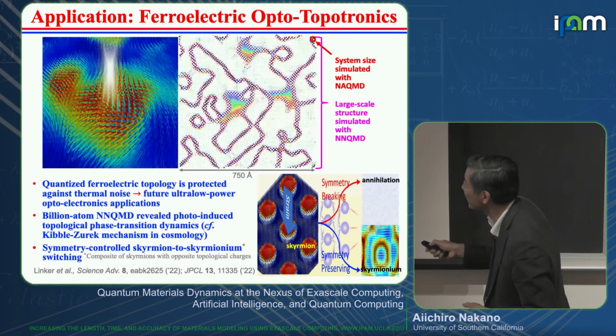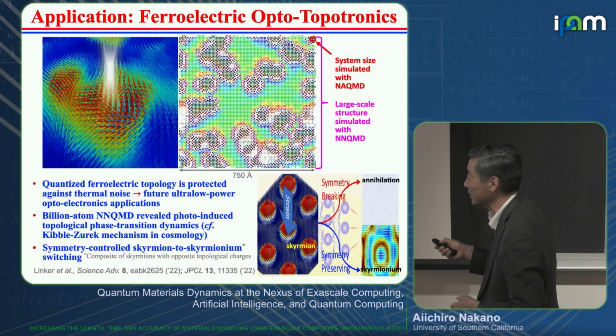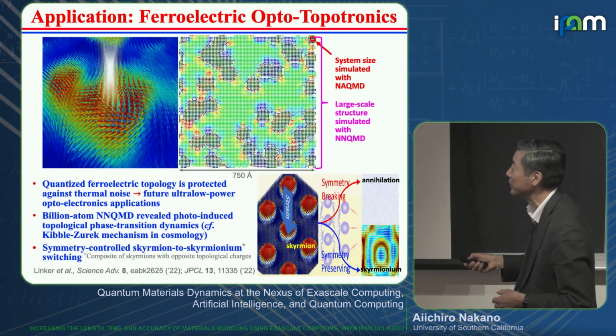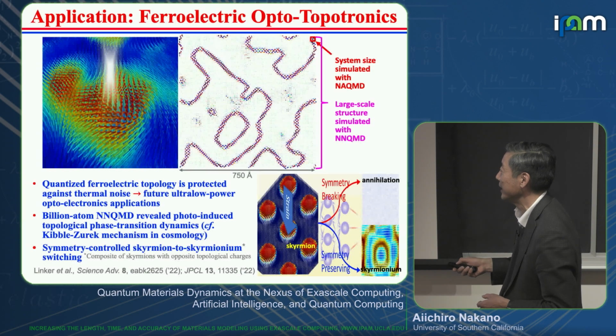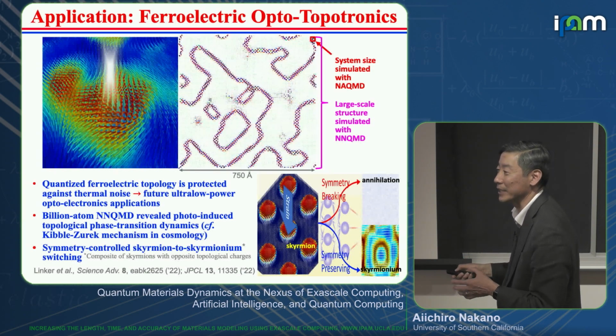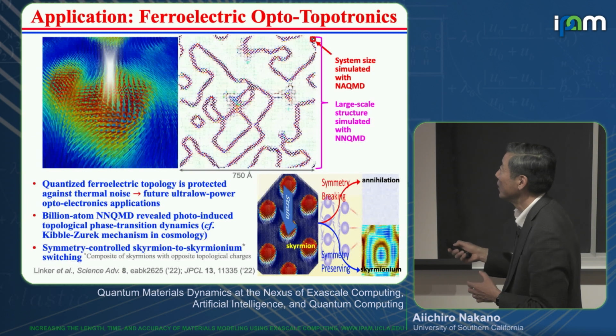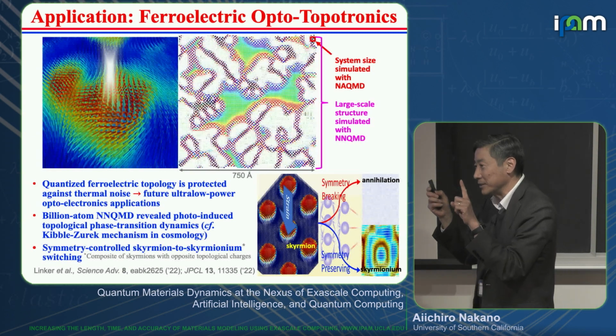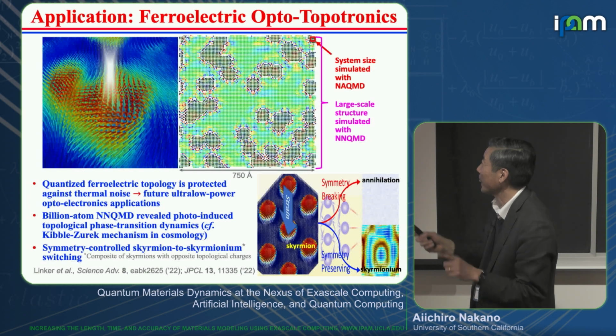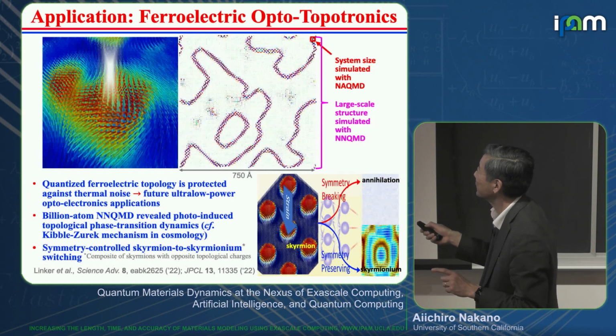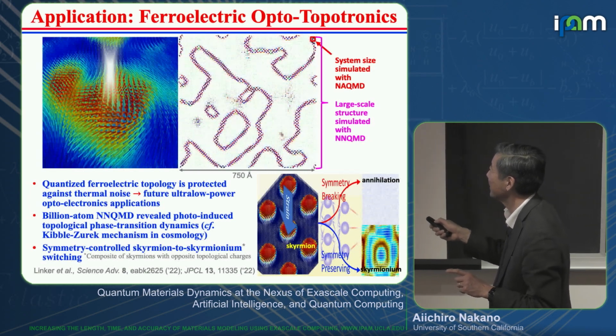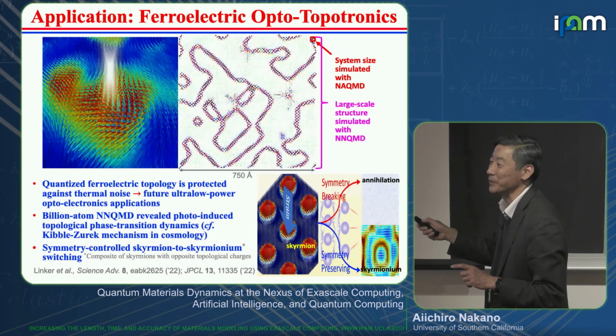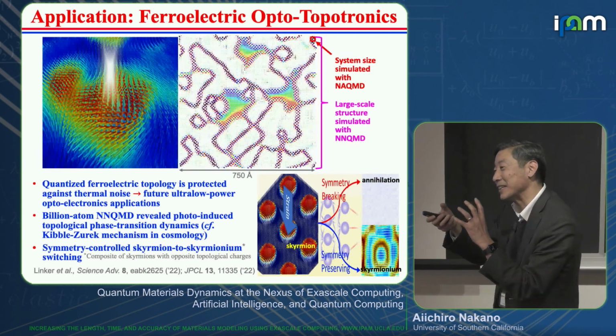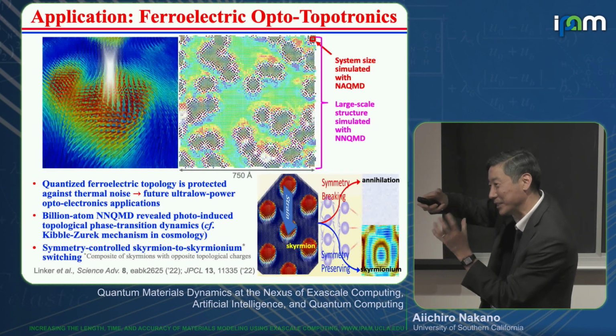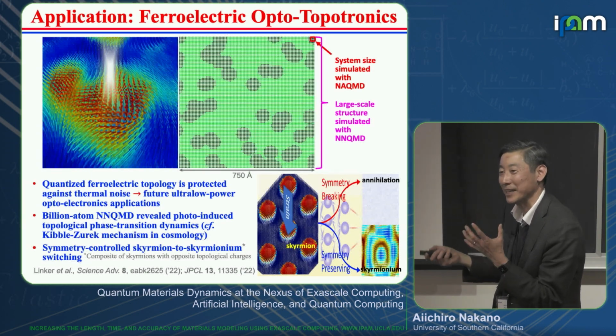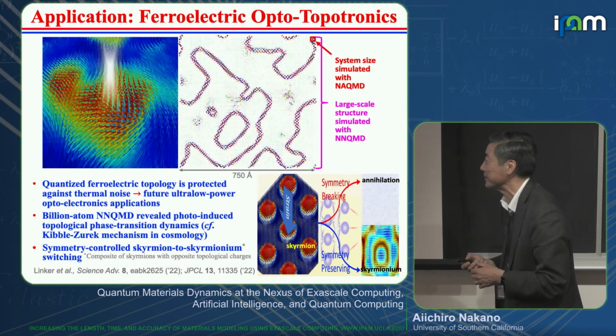And then our billion-atom excited state neural network QMD simulation revealed photo-induced topological phase transition and dynamics. This is similar to the so-called Kibble-Zurek mechanism. So with photoexcitation, this ferroelectric order is destroyed. It will create a kind of defect, and this is called a cosmic string. And at the same time, it creates another kind of tilting order parameter. So this is the photoexcited change of the order parameter.